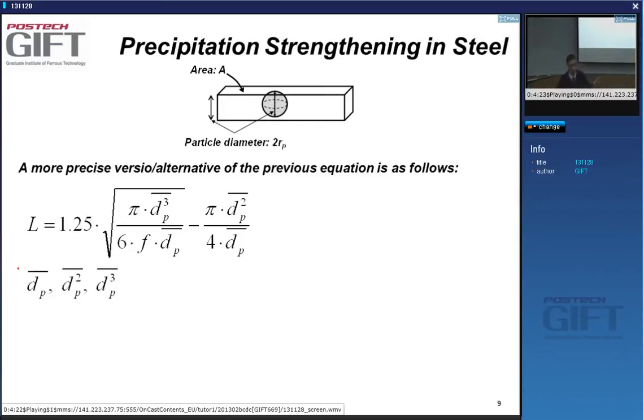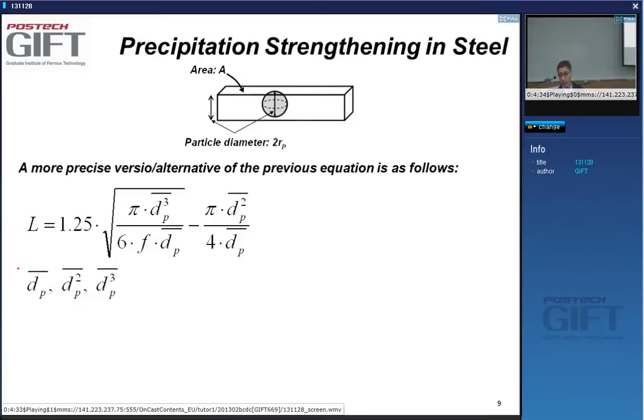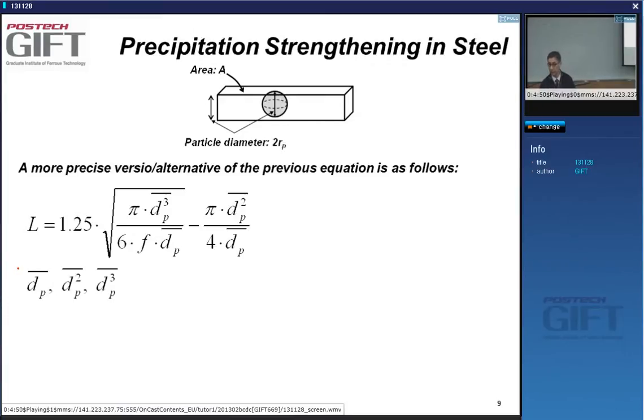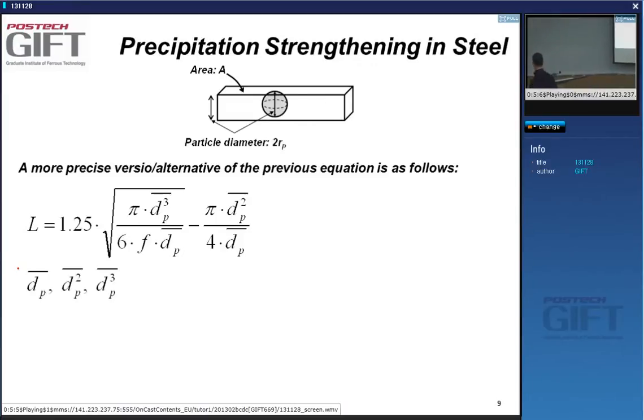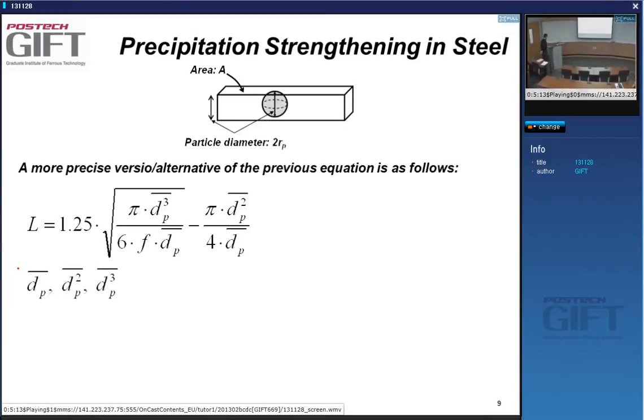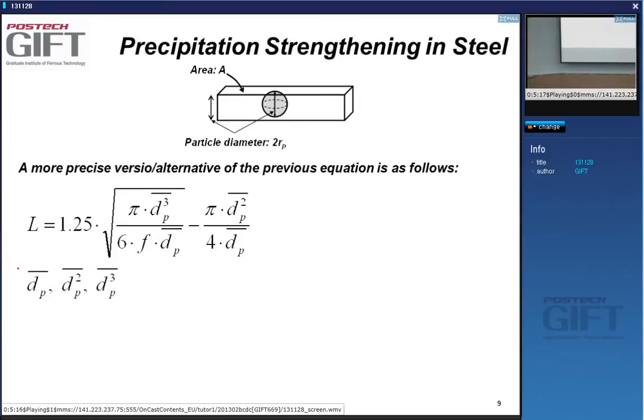By TEM measurements, for instance, you can determine the particle sizes and calculate the mean value. You make a column with particle diameters, a column with the squares of these measurements, and a column with the cubes. Then you measure the mean value of these three columns, giving the mean diameter, mean square diameter, and mean cube diameter. Substituting into the formula gives the stereologically correct value — that's the formula I would use for a PhD.